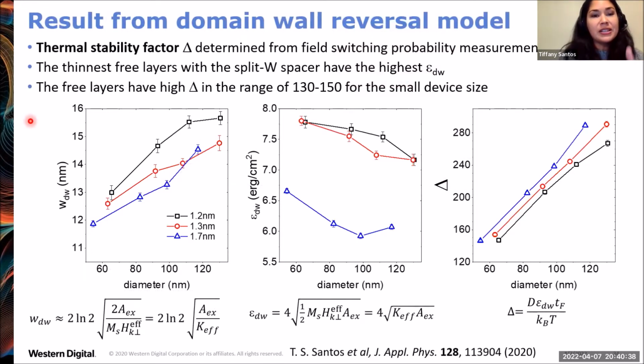And what we wanted to measure from our devices is the thermal stability factor and the switching current density. So here are the results for the thermal stability factor. It was determined from field switching probability measurements, where those results were fit to a domain wall reversal model, because for these sizes of devices, we're in the domain wall reversal regime. This analysis gives the domain wall width, the domain wall energy density, and the thermal stability factor, found by taking the domain wall energy density multiplied by diameter and free layer thickness over kBT. And we found that it is the thinner free layers with the better magnetic properties that give a lot higher domain wall energy density, and therefore they are able to maintain high thermal stability even though the free layers are quite thin.